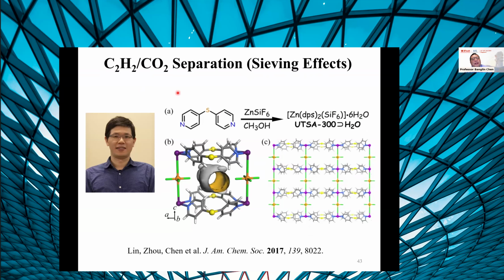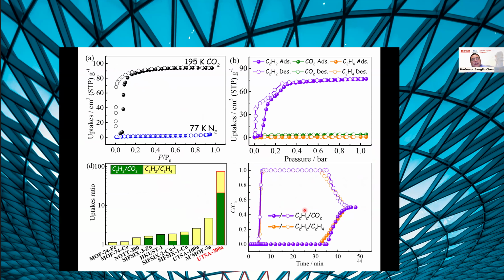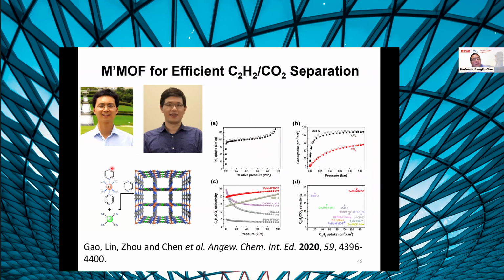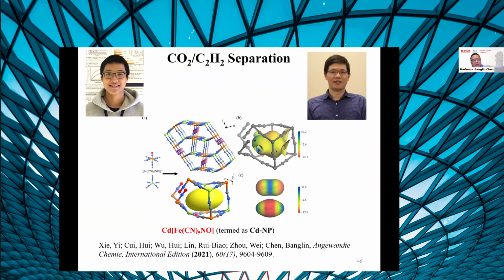And we also develop other materials, for example, for acetylene carbon dioxide separation, by sieving separation, very good sieving separation. And we can also use less amount of organic linker for this separation. And nowadays, we can even use still porous material, but without any organic linker for carbon dioxide acetylene separations. And so now you will witness the science development on coordination chemistry to coordination polymer, metal organic framework, and then here back to the traditional porous material. We hopefully can save the cost of organic linker, and also this material is kind of stable.